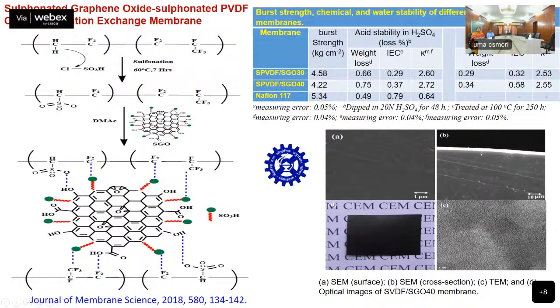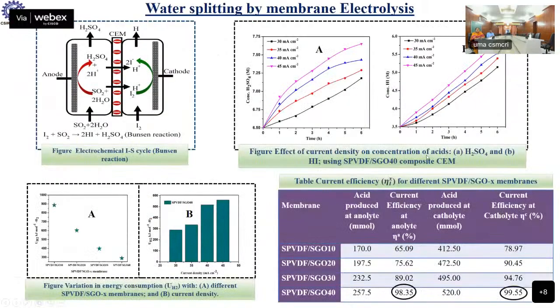PVDF-HFP was first sulfonated in the presence of chlorosulfuric acid, and then this sulfonated PVDF-HFP was blended with different amounts of sulfonated graphene oxide, and then the composite membrane was developed. The membrane is showing good acid and hydrolytic stability, and the morphology is also clear. This membrane was also used to see the water splitting phenomena at different current densities, and we have also calculated the amount of acid produced. In this case also the membrane is showing very good potential to be used for hydrogen generation by the Bunsen reaction.